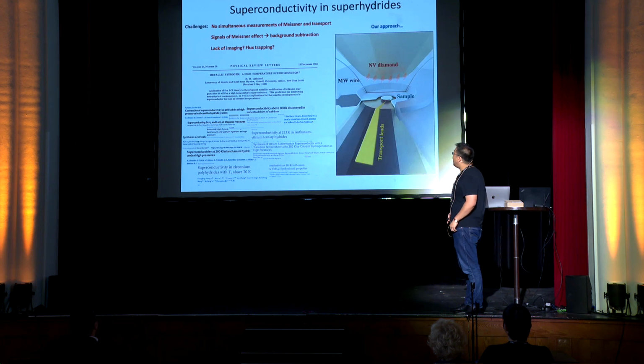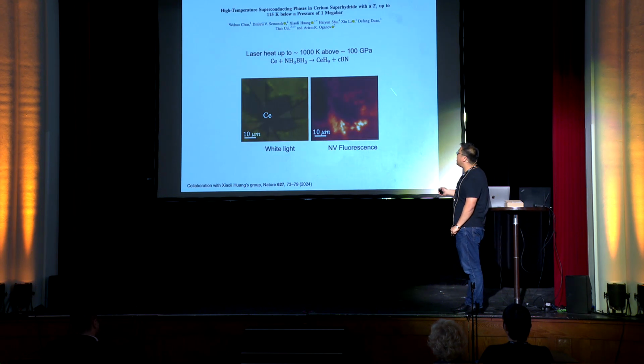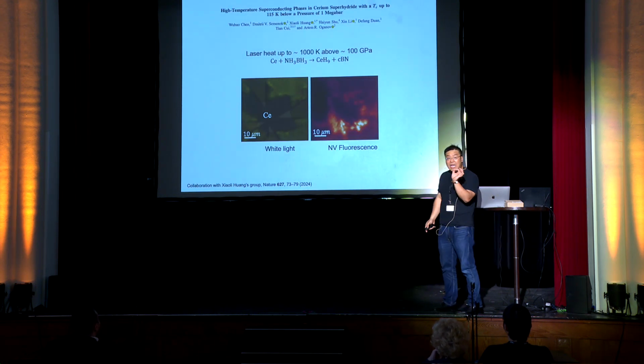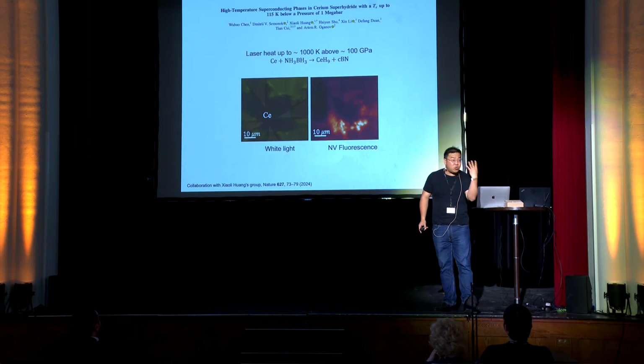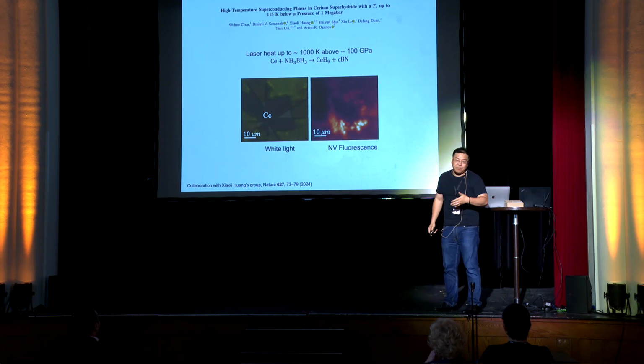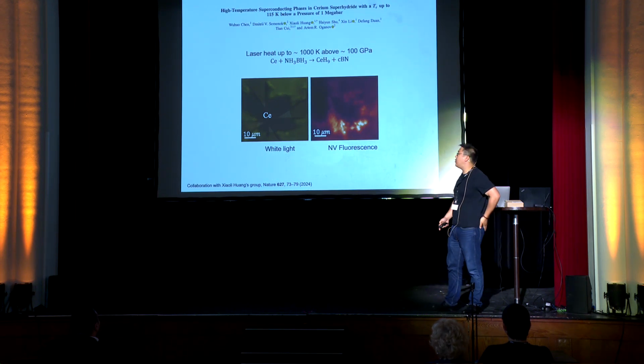And so my group has been working on a particular material, cerium hydride, and actually doing a combination of transport as well as local magnetic field imaging to understand where exactly in the sample chamber one is seeing superconductivity. We see lots of nice things, evidence of flux trapping. We see the ability to expel magnetic fields on field cooling and zero field cooling.